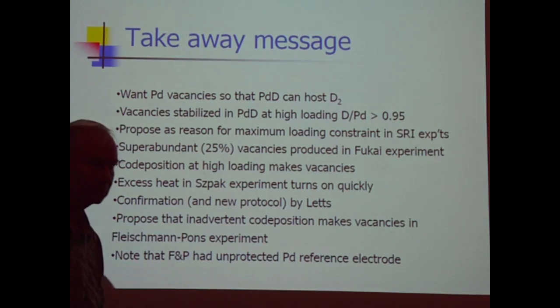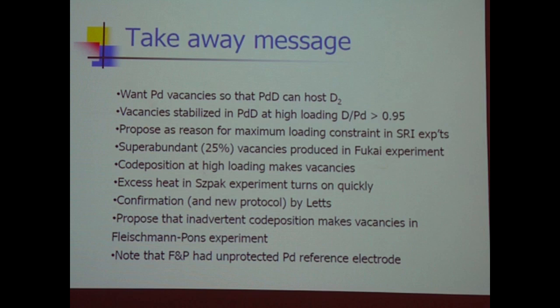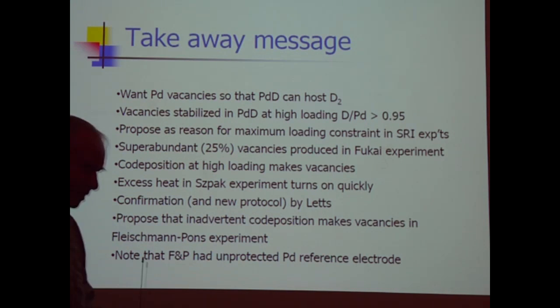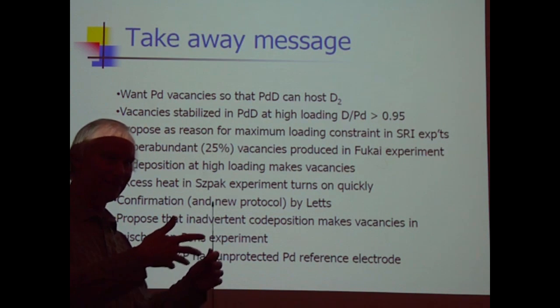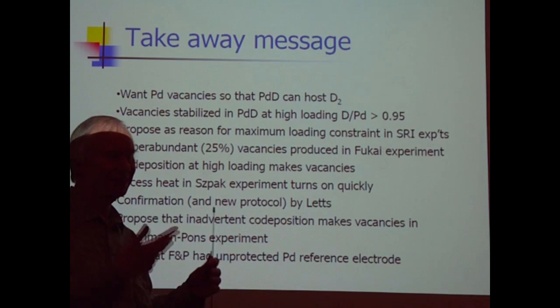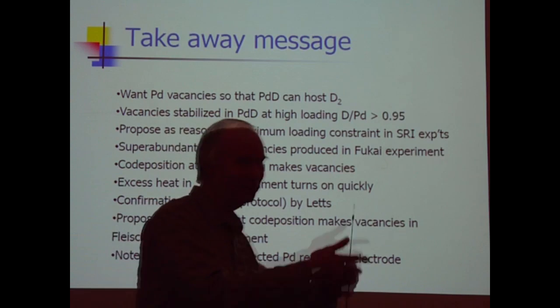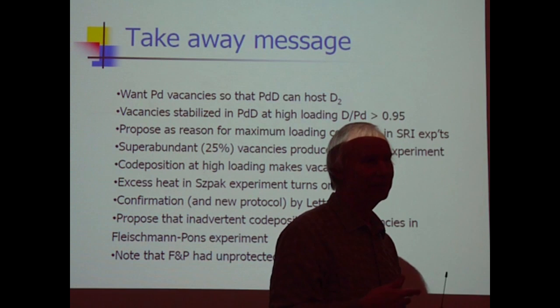I don't know. In the Fleischmann-Pons experiment, did they have excess heat turning on relatively quickly, a la the co-deposition experiments by Letts, or was it more of a month-long build-up? Oh, in the Fleischmann-Pons experiment, the early 1989-1990 experiments, you start out loading at low current density, very gentle for your cathode, for the diffusion arguments I gave and the destruction of cathode arguments that I gave earlier. And then you bring it up and you get high loading. And then you hope that excess heat comes. If excess heat doesn't come, you turn it down, you play with it, you bring it up again, you try again. And if you don't see anything, then you try it again. So a typical experiment would go on in this kind of fashion for a month or 6 weeks.